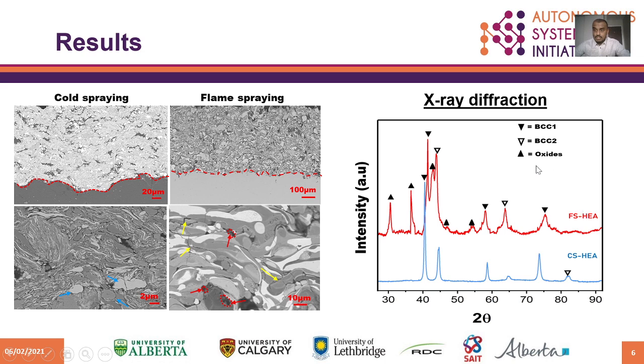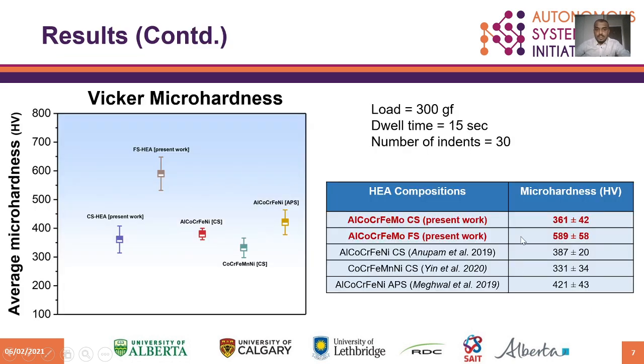Interestingly, the flame spray showed the presence of oxides, and the oxide formation is mainly attributed to the in-flight oxidation during spraying, which is not obvious for the cold spray HEA. The hardness study suggests that the flame spray exhibited a higher hardness, which is about 63% better than the cold spraying. And the high hardness is basically due to the presence of oxides.